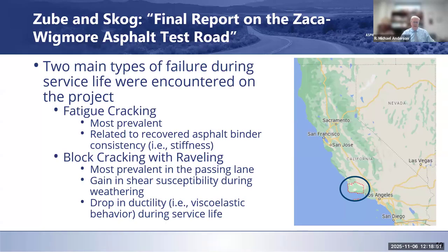But in 1969, there was a paper in the Association of Asphalt Paving Technologists Journal, AAPT Journal, volume 38, which was called Final Report on the Zaca-Wigmore Asphalt Test Road by Zube and Skog. And in that, they looked at this test road that was placed in the 50s and monitored going into the 60s. And they found that there were two main types of failure that occurred during service life on the project.